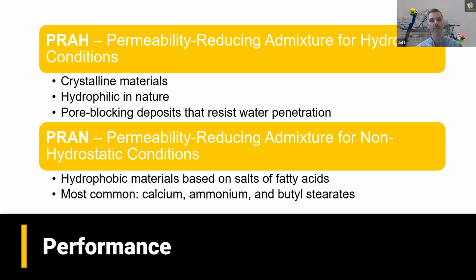Now, these would be different from a permeability reducing admixture for non-hydrostatic conditions, or a PRAN. This type of product would normally be a hydrophobic material, something that provides some low absorption, water repellency, kind of like a rain screen effect. Now, these can be good for above grade use, reducing efflorescence, but they don't actually block the pores. So if there's ponding water or hydrostatic pressure, that water can still be pushed into the concrete. So only a PRAH would be suitable for a waterproofing application.